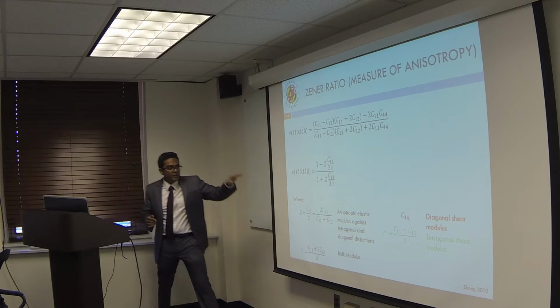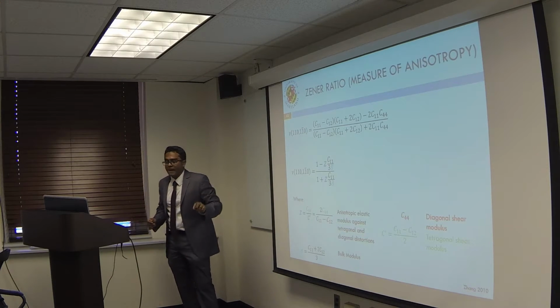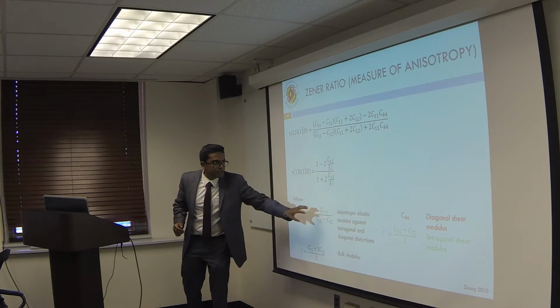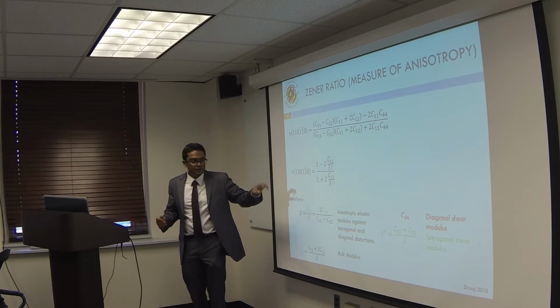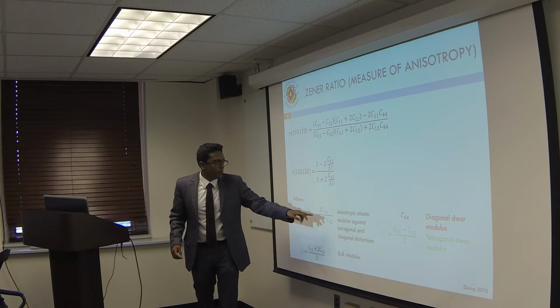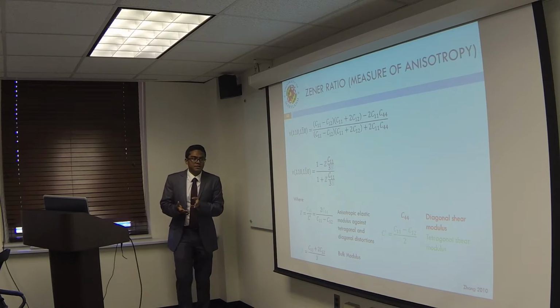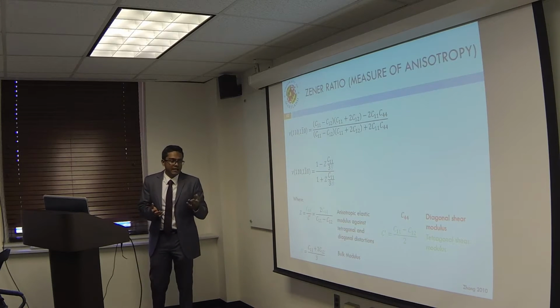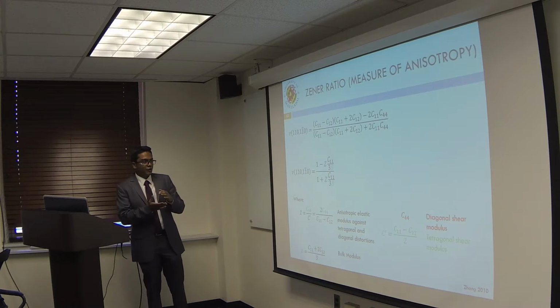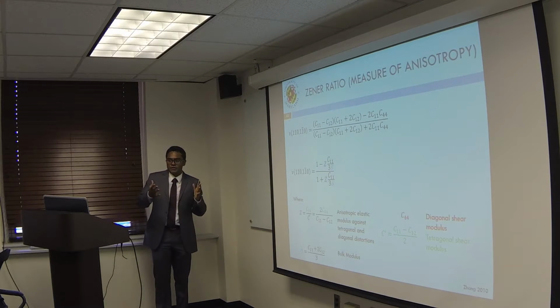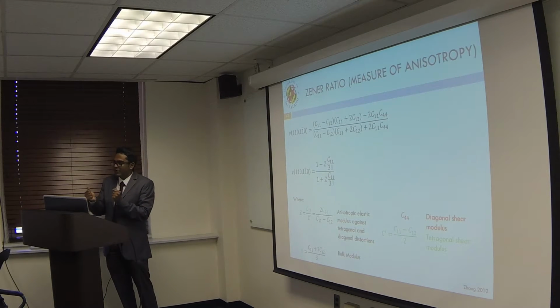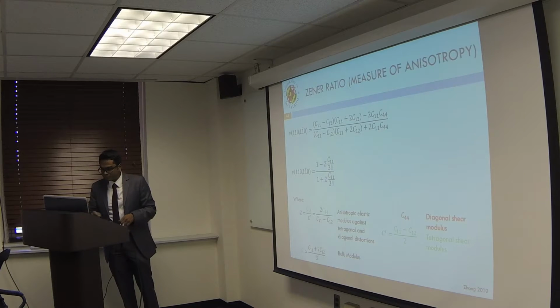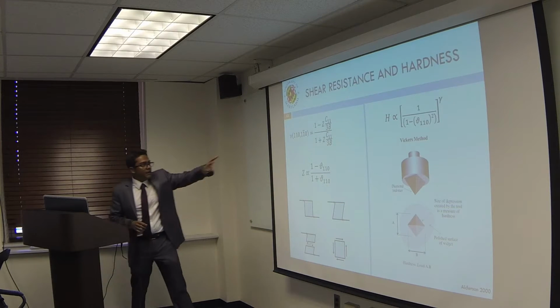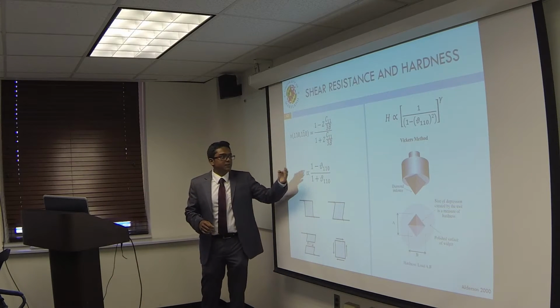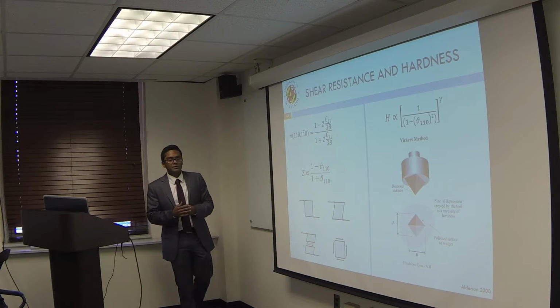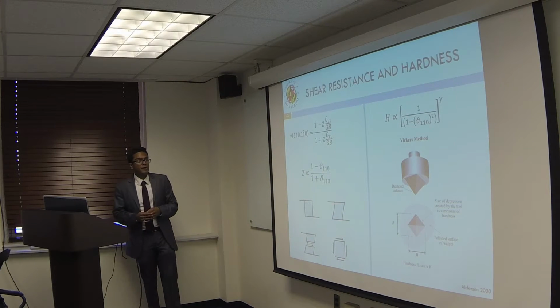So in isotropic materials, this ratio goes to 1. And this essentially determines the shear strength of the materials, because (C11 minus C12)/2 is the tetragonal shear modulus, and C44 is the diagonal shear modulus. And the ratio of this gives you the Zener ratio, which determines how resistant the material can be to shear. So when I rearrange the terms, it turns out that Z is proportional to (1 minus Poisson's ratio) over (1 plus Poisson's ratio).